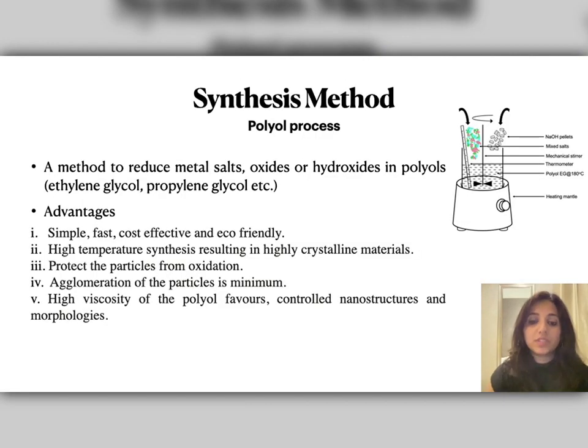Iron-based alloys could be synthesized through various techniques like ball milling, thermal decomposition, hydrogen plasma metal reaction, etc. But they have disadvantages like agglomeration, strain-induced effects, prolonged synthesis duration, difficulty with composition control, etc. Thus, we have used the polyol process as a synthesis technique, which is an instant chemical reduction technique and is a much simpler, faster, cost-effective and eco-friendly technique that is used to obtain non-equilibrium phases.